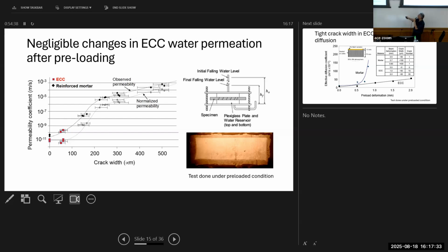Okay, so that forces the liquid, the water in this case, to go through the specimen, especially through the micro cracks, and we collected the water on the other side in a reservoir as a function of time, and then deduced the permeability. Now, what this chart shows is the permeability measurements as a function of the width of the cracks. And you can see that for the ECC specimens, they all cluster below 100 microns. And that's because the material self-limits its own crack width. No matter how much imposed load I put on, the crack width is tight in ECC. So they're all in this region here, below 100 microns.